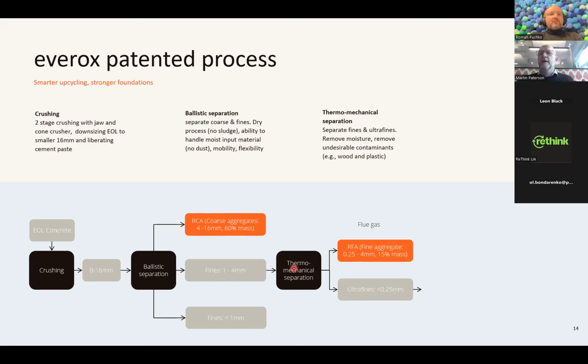So it's a very efficient way of cleaning the sand, and accordingly we get a very dry and clean sand out of it, high quality with a water absorption actually below 6%. We call it recycled fine aggregates. That's the orange one here. And the cracked off cement paste, we call it the ultra fines.